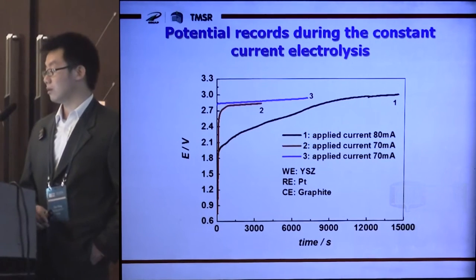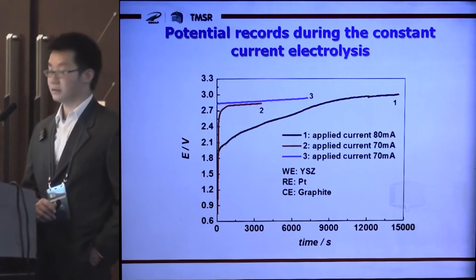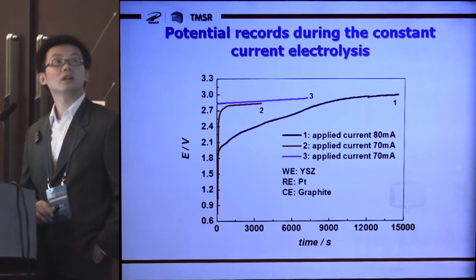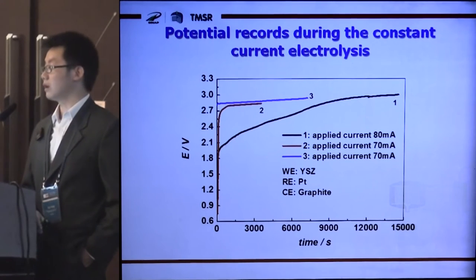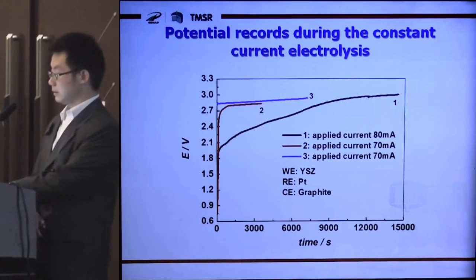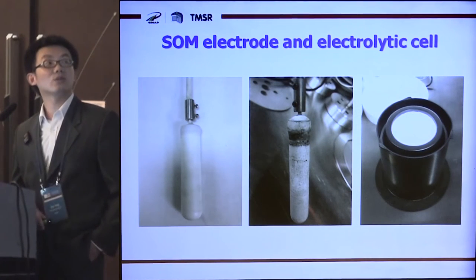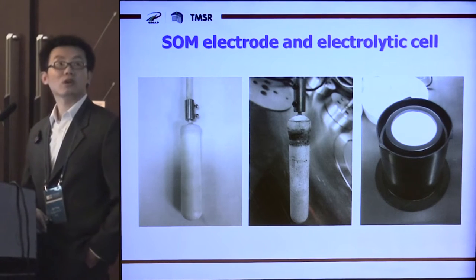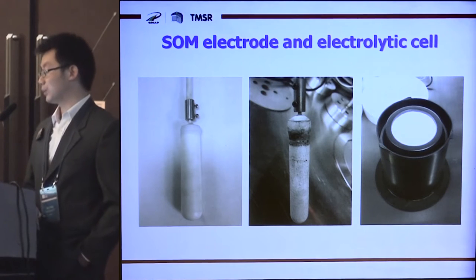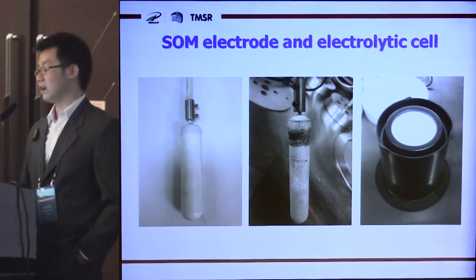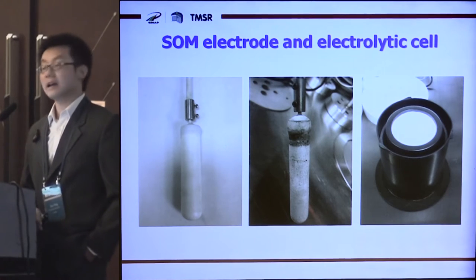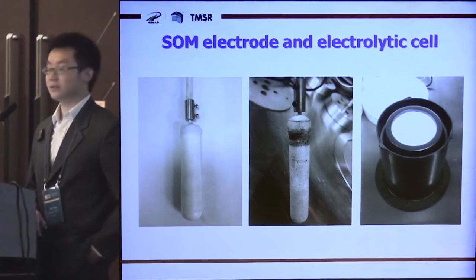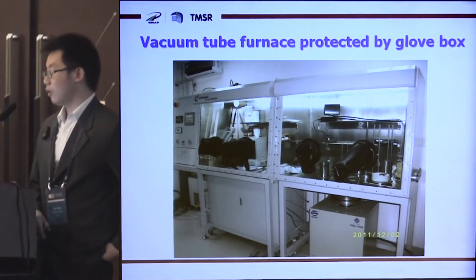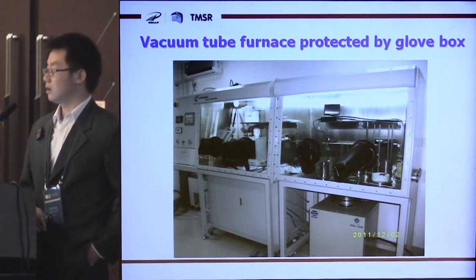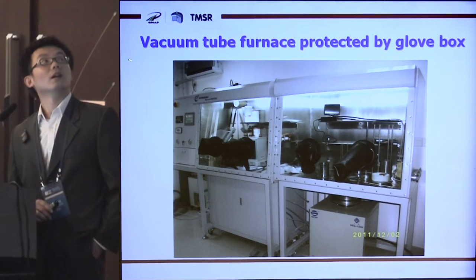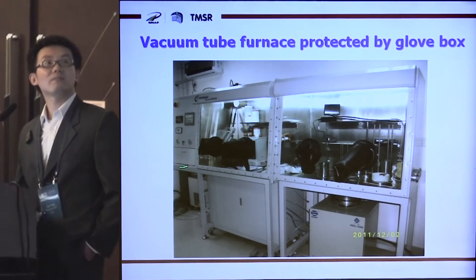This is the potential record during the constant current electrolysis. The potential was controlled not to exceed 3 volts to avoid side reactions. And this is the SOM electrode before and after electrolysis. More work needs to be done to examine the performance of the SOM electrode. And this is the electrolytic cell employed in the experiment. All of the high temperature electrochemical experiments were carried out in a vacuum tube furnace protected by this glove box.